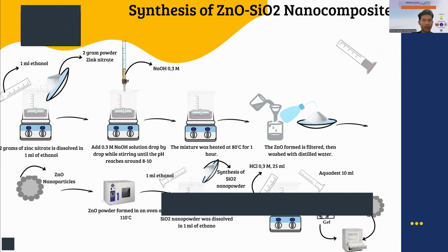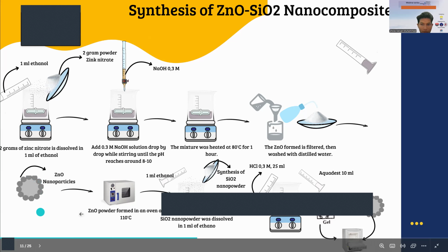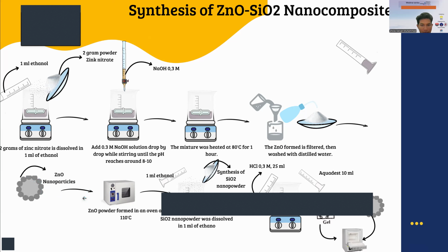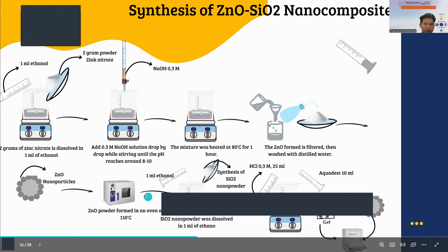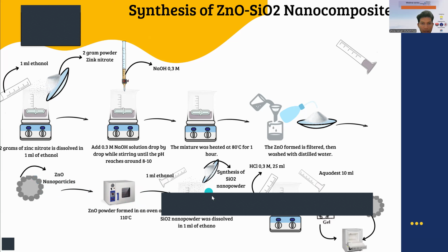Next step, the ZnO form was filtered using filter paper, then washed with distilled water. Next step, the ZnO powder formed was oven dried at 110 degrees to remove water content in this ZnO nanoparticle. Next step, the synthesized SiO2 was prepared in the form of a gel by dissolving SiO2 nanopowder in 1 milliliter of ethanol.